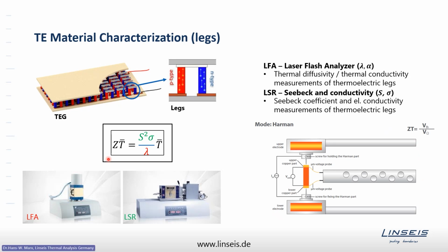Let's have a look how this Harman method works. You feed electrical current to the thermoelectric material, and you measure again the voltage throughout this material. And the voltage as a function of the electrical current is plotted, and the thermoelectric voltage can be separated. We will see this later, how this is done. The thermoelectric voltage can be separated from the ohmic voltage drop, and by dividing one by the other, you get directly the figure of merit.